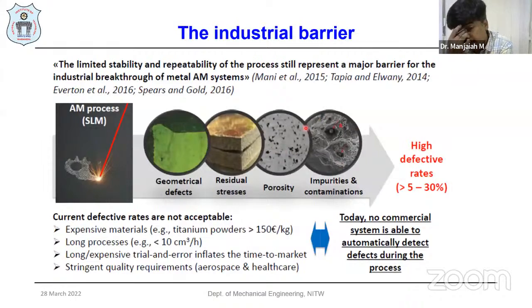And porosity is very common in the additive manufacturing process. To avoid or eliminate the porosities is very difficult. Here the defective rate is more than 5%. We are getting 5 to 30% of defective rate. But commercially today, it is difficult to accept this kind of defective rate. We need to have a very, very low defective rate even in aerospace or healthcare applications, because stringent quality requirements are there. That's why it is very much required. It cannot be acceptable. And today, there is no commercial system available to automatically detect the defects during the process itself. That is where developments are required.